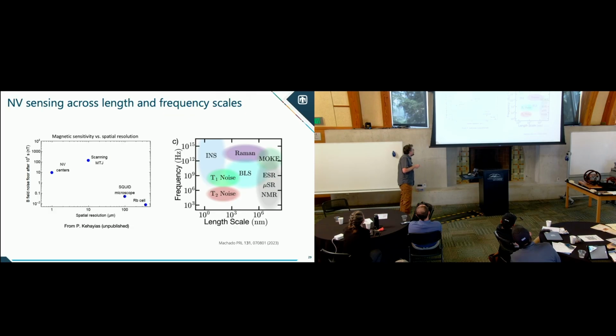So you can get, and this is from an imaging mode, this does not include scanning, which goes a couple orders of magnitude lower even. And so you sacrifice your sensitivity to gain high spatial resolution. Now this is kind of DC sensing. The AC sensing is more the coherent effects with T2 type noise. And then you can also look at broadband through T1 type noise. And we'll talk a little bit more about that. But the point is you're also beating out, and this is for more condensed matter type systems, ESR, µSR, NMR live up here. Here you're getting down to lower length scales again with good sensitivity. Okay.